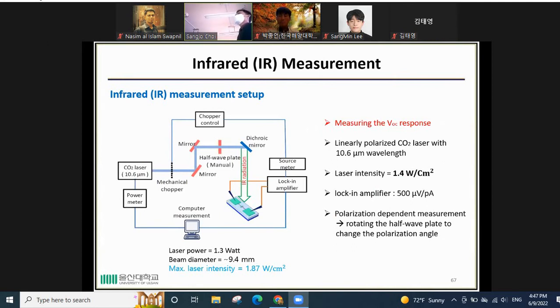And then the second measurement is infrared measurement to measure the VOC response of the device. We use a linearly polarized carbon dioxide laser with 10.6 micrometer wavelength, and this laser is passed through a mechanical chopper to form a square wave, and then synchronize the lock-in amplifier. In this laser we also use a laser intensity of 1.4 watts per centimeter squared. And for polarization dependent measurement, we rotate the waveplate to change the polarization angle of the incident wave.